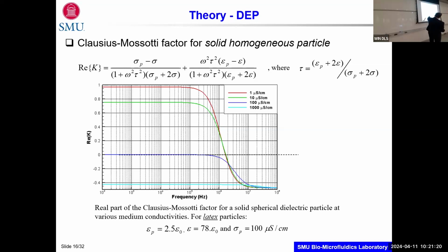So we did this, theoretically, looking into different conductivities of the buffer, and you have a very interesting, say, pure or ultra pure DI water, which will be hard to have in a lab, but you will have a 1, and then it transitions within this frequency range and becomes negative half. However, after some sort of threshold, you may not even see any positive DEP, and then high frequencies may give you negative DEP, or in a very highly polarizable fluid, you will only see negative DEP for these particles. So as I tried to allude to, if the real part of the Clausius-Mossotti factor is positive, you have positive DEP, otherwise you have negative DEP.